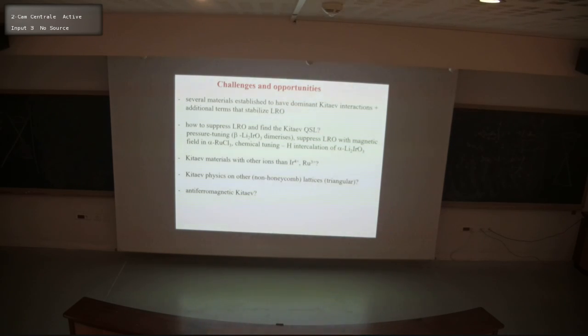Another possibly interesting point is that for all of the materials so far, the community agrees that the Kitaev interaction is ferromagnetic. However, the phase diagram of antiferromagnetic Kitaev, in particular the field behavior, is much richer, and so it'd certainly be very interesting to look for materials that could realize that.